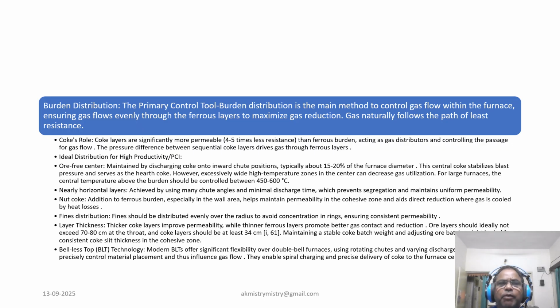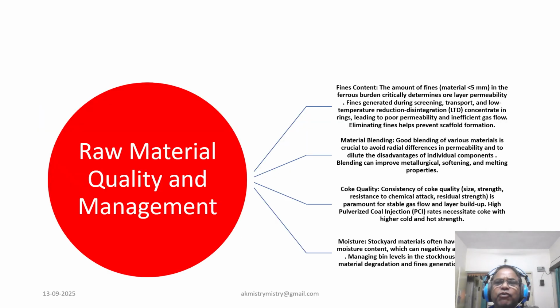And so to optimize this primary control, we follow several ideal practices. For higher productivity, we aim for an ore-free center maintained by discharging coke onto an inward chute position, typically about 15-20% of furnace diameter. This central coke stabilizes blast pressure and serves as hearth coke. We also strive for nearly horizontal layers achieved by using many chute angles and minimal discharge time. This prevents material segregation and maintains uniform permeability throughout the burden. Nut coke can be added to the ferrous burden, especially near the walls, to improve permeability in the cohesive zone and assist direct reduction.